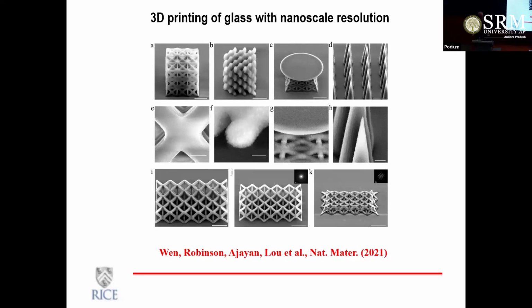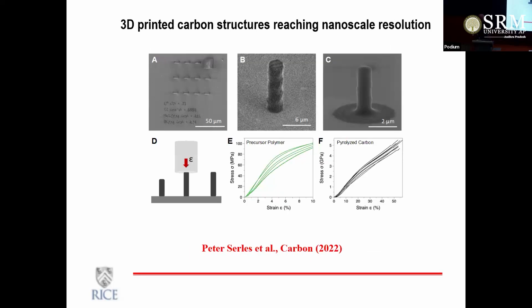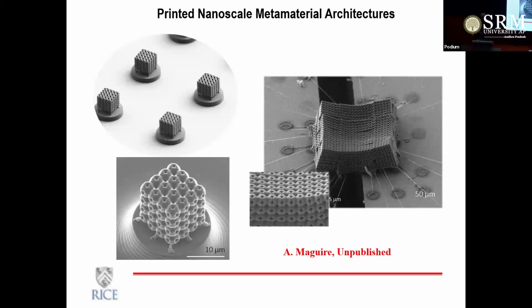The question I was asking some of the students is, can you actually print a carbon nanotube, right? That will be a revolutionary thing if you can actually do that, right? Because then you can do exactly what you want. We haven't been able to print a carbon nanotube, but we have been able to print some carbon nanowires and rods that are in that range that you're talking about. Still not there yet, but at 100 nanometers, 200 nanometer resolution, you can print a carbon material pretty nicely. Here are some of the structures that we have printed in very recent times. You can really create very complex carbon-based architectures using 3D printing, reaching less than 1 micron resolution. And with further refinement and improvements, I'm sure you can get to address the question that I was asking, whether you can really get to nanoscale printed carbons. And then again, really interesting materials can evolve.